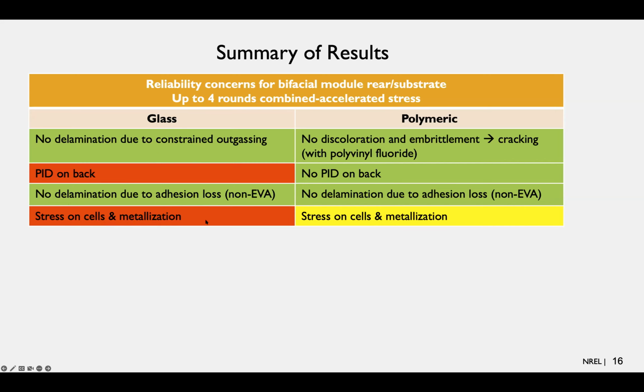In an important way. With the polymeric backsheet, we did not see any discoloration or embrittlement or cracking of the backsheet. In all cases, it was with polyvinyl fluoride backsheets, either clear or white. Of course, we only ran up to 4 rounds of combined accelerated stress testing, which might be like 5 years in the field. So it's not 20 years worth of testing we did, just to clarify that. We saw no PID on the back when using the polyvinyl fluoride backsheet. We saw no delamination due to adhesion loss. And we did see some mild stress on the cells and metallization, because we did see an increase in grid finger breakage with the polymeric substrate as well, even though it was 3 times more with the glass substrate.